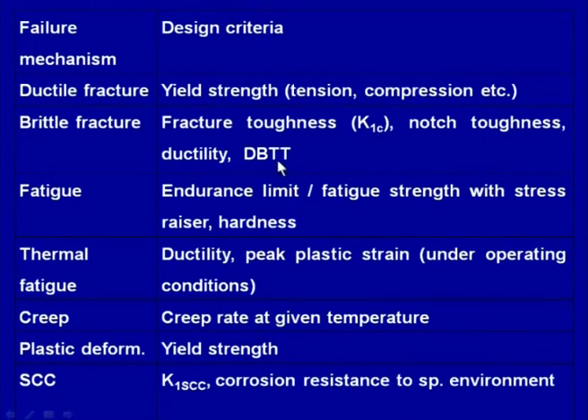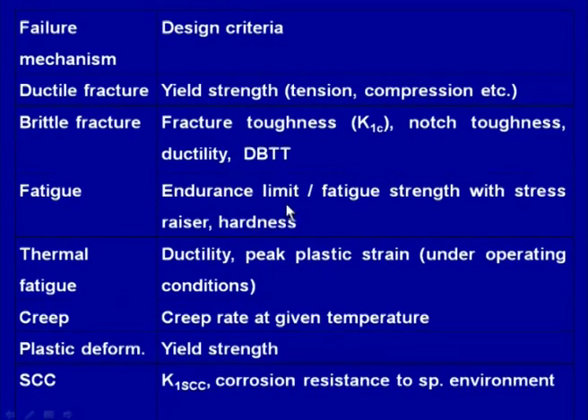This is the particular temperature at which there will be a sudden change in the toughness of the material, and it decreases abruptly from a high value to a low value. So that temperature band at which the sudden change takes place is called the ductile to brittle transition temperature. Then the fatigue: if the component is expected to fail by fatigue, then the endurance limit and the fatigue strength of the material with the stress raiser should be used as a design criteria, and the hardness should also be considered, because it dictates significantly the crack nucleation and the growth stages of the fatigue fracture.